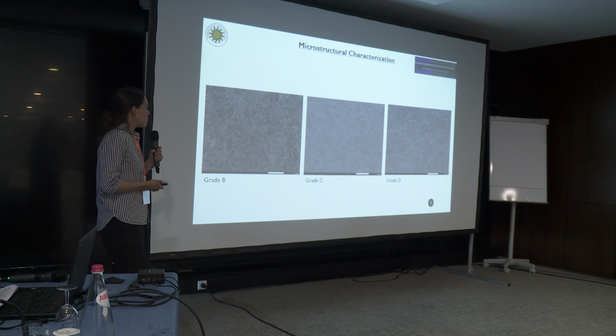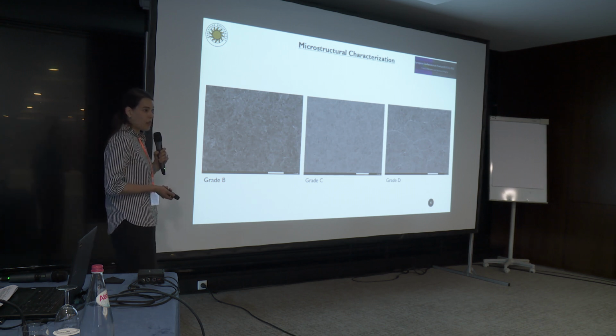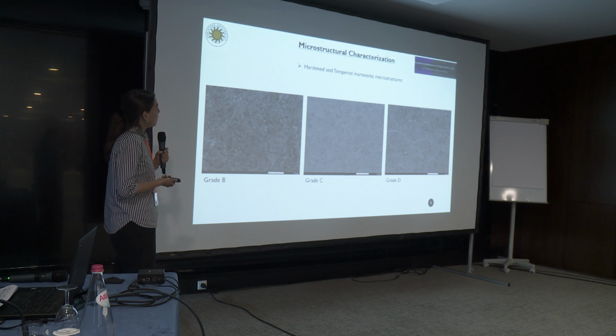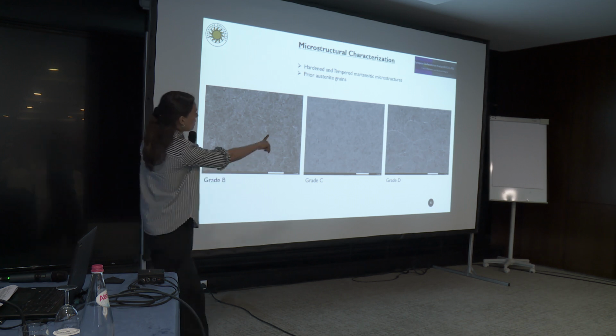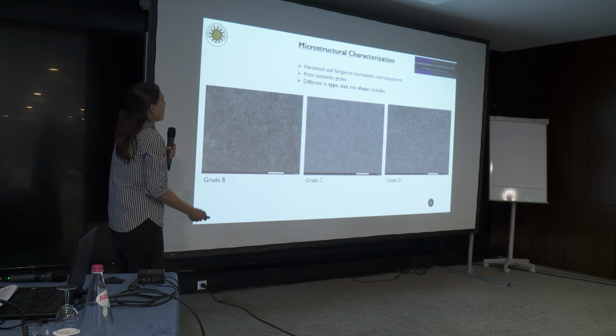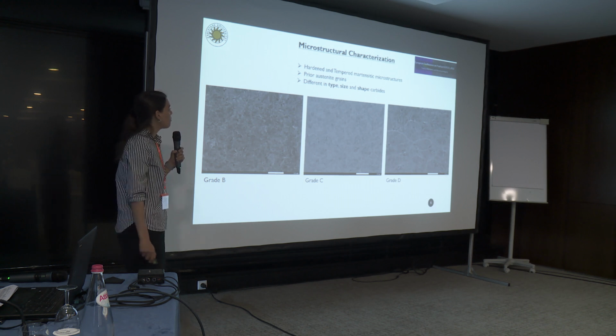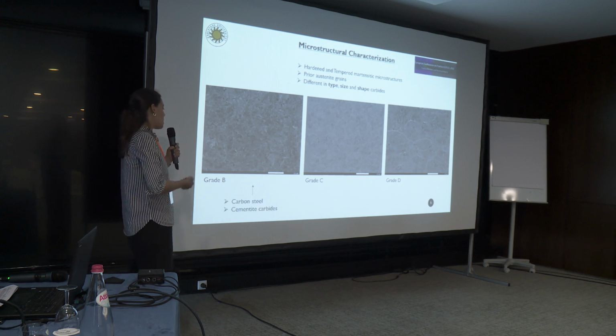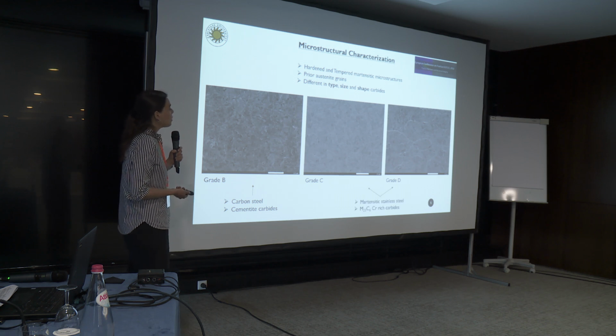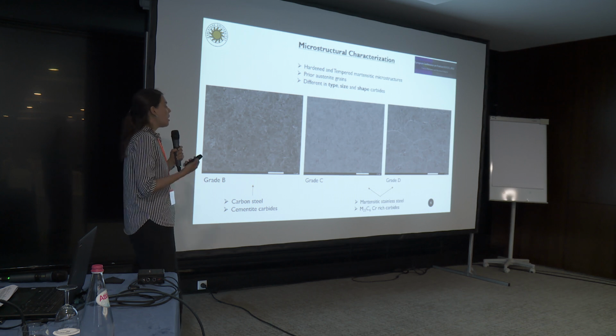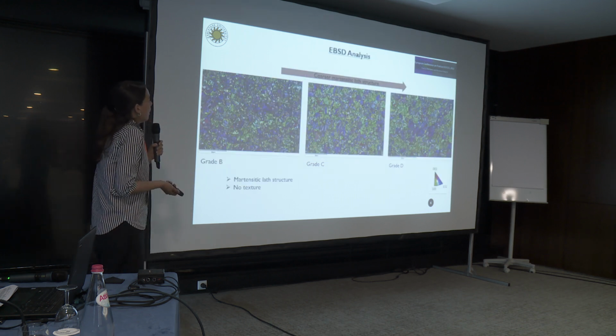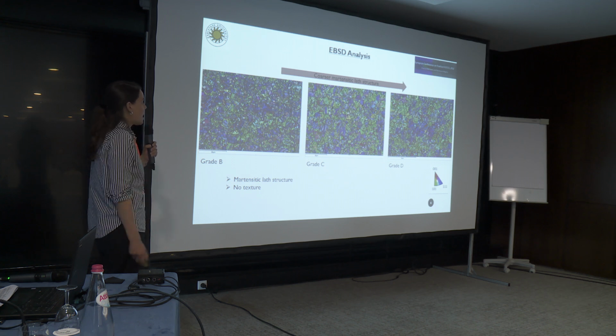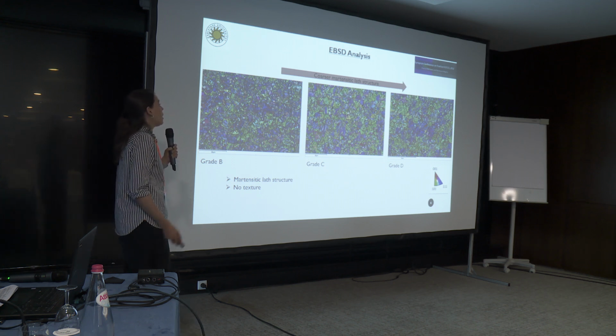So I will start the results with grades B, C, and D, since they have the same thickness. They are hardened and tempered martensitic microstructures with the prior austenite grains being obvious, especially in grade D. Here we have carbides different in type, size, and shape. Grade B is a carbon steel with typical cementite carbides. Grades C and D are martensitic stainless steels with M23C6 chromium-rich carbides.